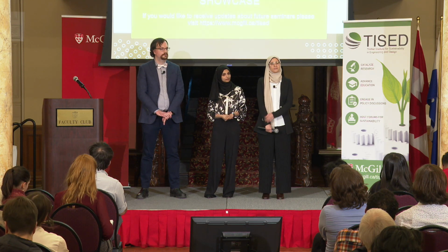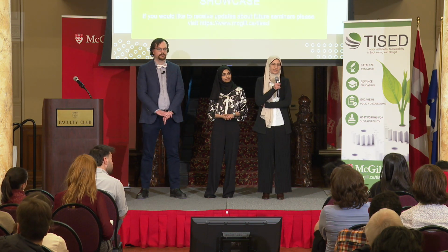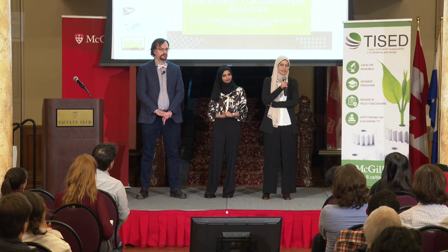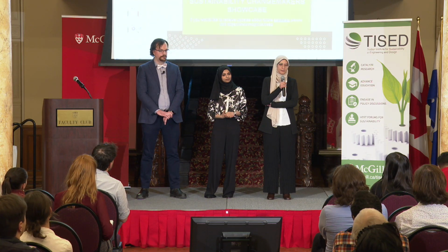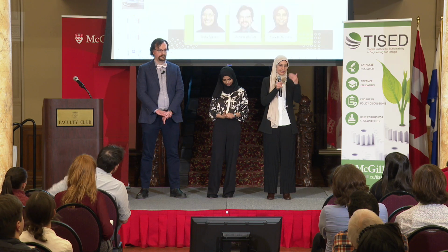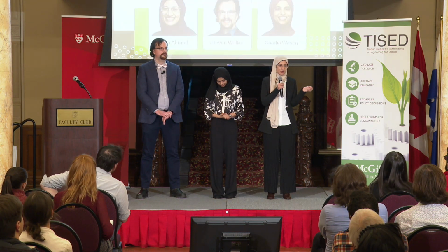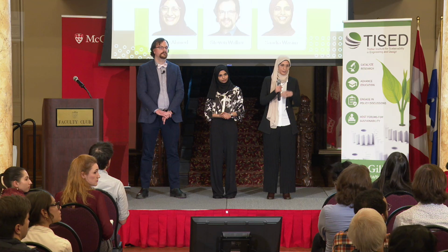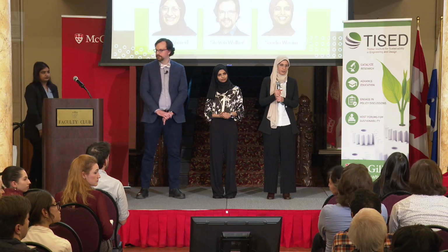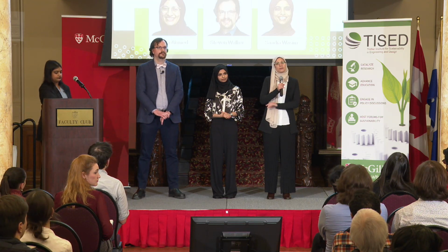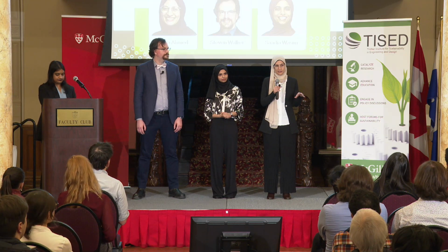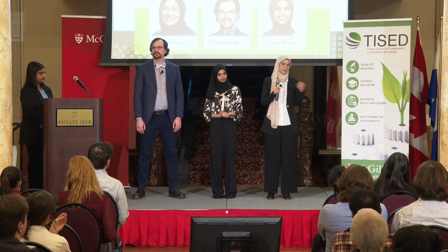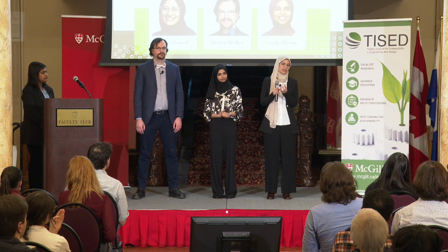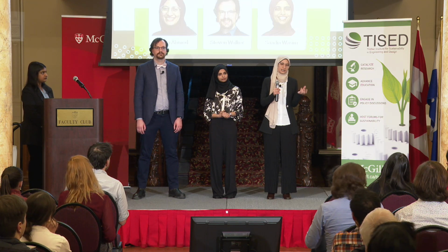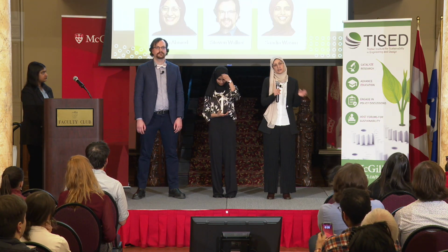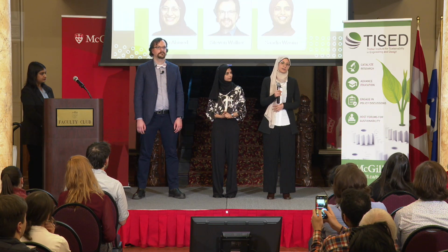On the environment? Thank you for your question. So if I understood you correctly, you are asking if during mixing, instead of heating the material, we can use another synthesis method to mix — are we just heating, or also mixing and applying other types of processes? So in the beginning, we mix the precursor, initially in a machine called ball milling, just to mix the precursor. Then we make sure that everything is homogeneously mixed. Then we apply the heating — take an amount of this precursor and heat the mixture.